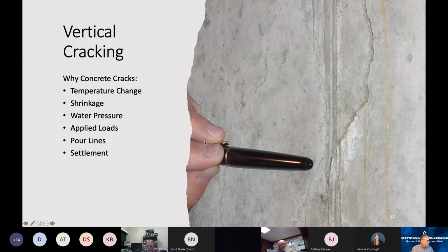Here's another one. This is a vertical wall. And this vertical wall crack that you can see, we're looking right at a form joint between two cast in place form panels, and then a crack that loosely follows that form joint running up or down the wall. And so again, the nature of these cracks, homeowner goes down, maybe the homeowner's trying to finish the basement, and what do they see in addition to the crack? And you can kind of see it with these tan lines that are coming off that. That's soil residue. Moisture's been coming through that crack. And so it's an indication of when a crack is problematic, and we'll be talking about that throughout because we're getting moisture coming through that crack.